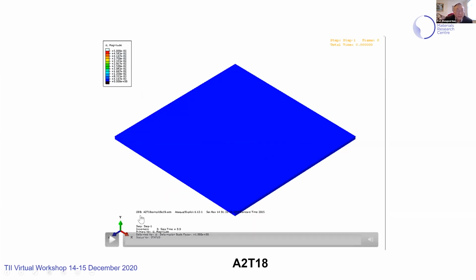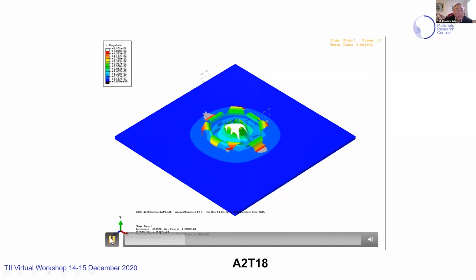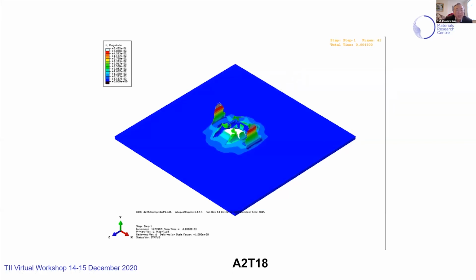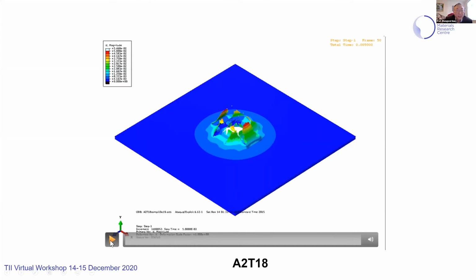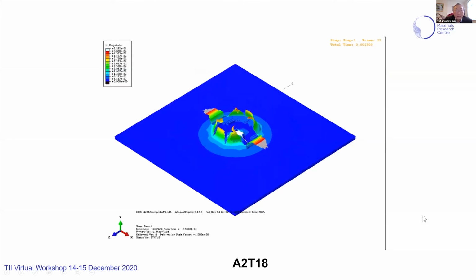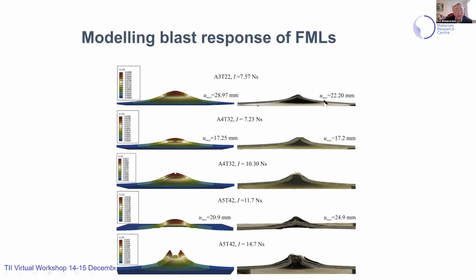This is another animation just showing the simulation of blast. This is the 2-1. So you get this kind of simulation, which captures a real situation. And now if we increase the thickness of the fiber metal laminates, from 3-2, to 4-3, and 5-4, we see that we have quite a different failure mode.